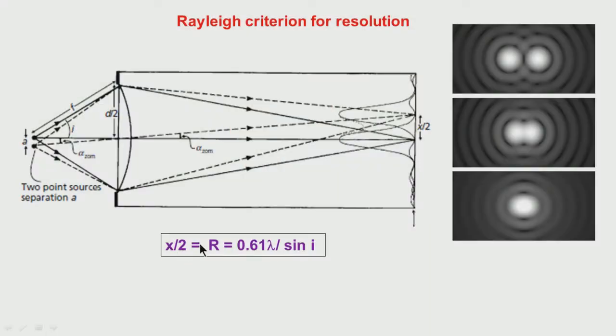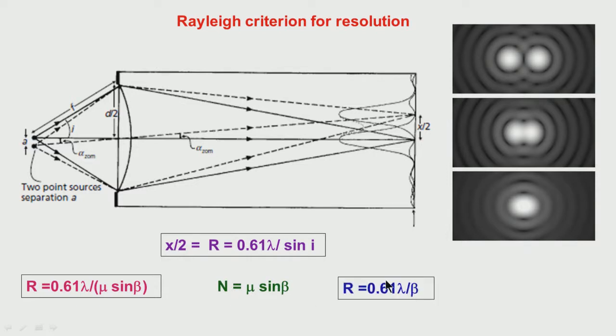So we can see that this distance r, with this derivation, turns out to be 0.61 lambda by mu sin i, with respect to the way it is drawn. Normally, we use beta for the maximum angle the object makes with the lens, so we write it as 0.61 lambda by mu sin beta, where mu is the refractive index of the medium. In an electron microscope, the refractive index is 1 and the angle beta is small, so it can be written as just 0.61 lambda by beta. This is how it comes.